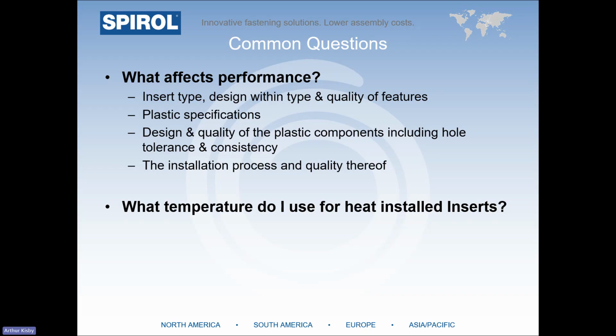Another common question we often get is, what temperature do I use for heat installed inserts, and what pressure should I apply? We recommend starting with a temperature 50 degrees Fahrenheit above the initial softening temperature for the plastic in question. But for plastics with fillers, its initial differential should be increased to about 150 degrees Fahrenheit. Pressure is insert size dependent and should be as low as possible, in the 5 to 15 psi range. And the pressure should be just enough to push the insert into the hole as the plastic melts.